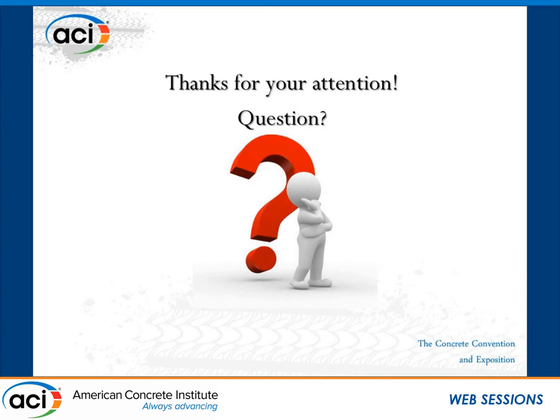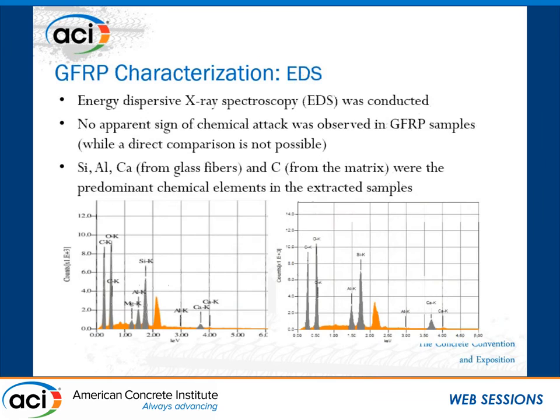In any human sample preparation, there is a consistency issue, right? So in order to be consistent, I performed the same procedure on control samples, pristine samples, right? No deterioration, nothing. And those spots were also still there, and in the EDS we don't see any chemical changes. So mainly they are part of the roughness of the surface, and you can see that. Let me show you here in this image.